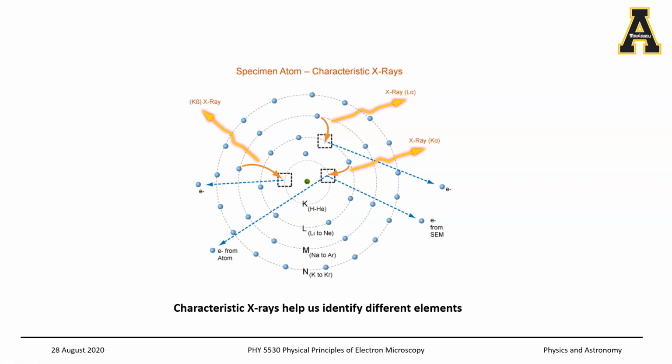So depending on the material, depending on the atomic number, the amount of energy that an electron releases when it is moving from one orbital, one shell to the other, is characteristic of that material itself. For example, if you think of sodium versus lead versus titanium, these are completely different atomic numbers, which means they have their own signature characteristic X-rays, right?